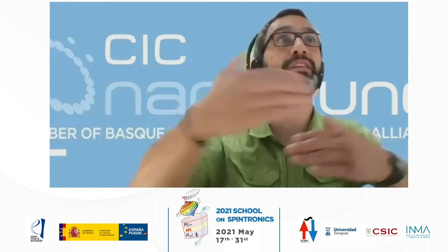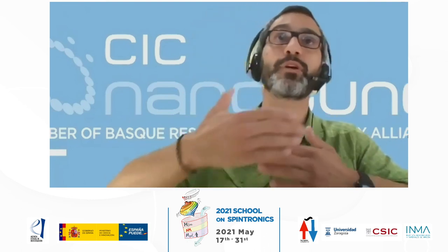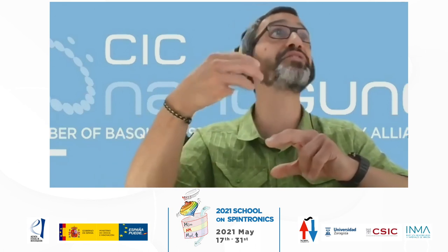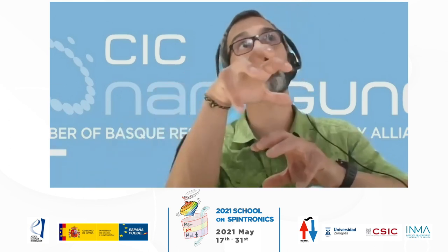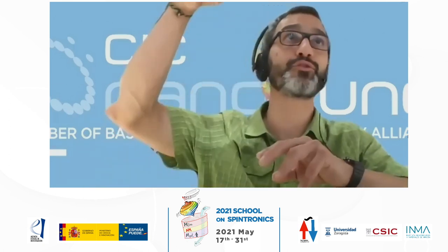The spin channel where you want to inject, whether semiconductor, metallic, or graphene, is very different, right? For graphene, you can use CVD graphene and pattern it, or you can exfoliate the graphene. In the case of semiconductors, it's typically more complicated. If you want high quality semiconductor, then you have to pattern it. But typically, if the material is very resistive itself, if the spin resistance of the spin channel is higher than the spin resistance of the ferromagnet, even if you try to inject the spin, most of the spin current will flow back to the ferromagnet. So effectively, you will not inject. Okay.